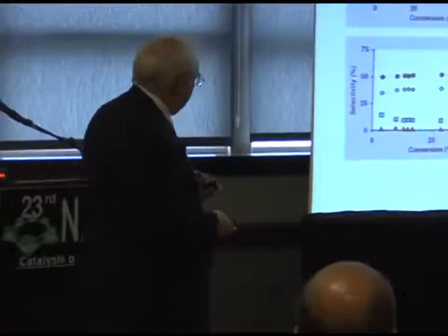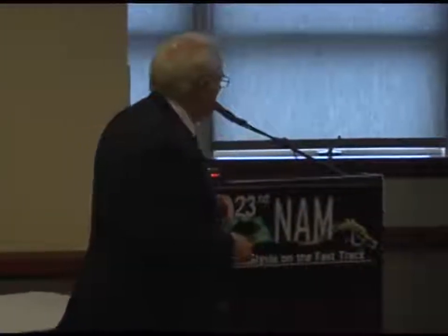So now let's go to the carbonylated dimer, and look. The butane selectivity is way less than 1%, all the way up to conversion of 50%. So we're suppressing the direct formation of some of these products. Now let's go further. Let's examine the secondary reactions by looking at some higher conversions.